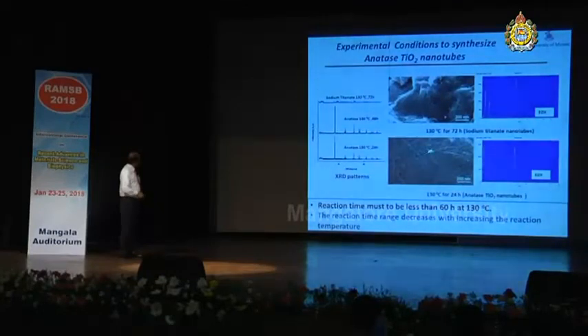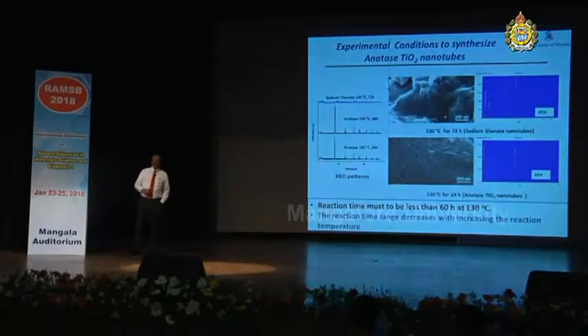This is the synthesis of titania nanotubes. There are so many papers on the synthesis of titania nanotubes, but what we have done is something different compared to what earlier people did. And in fact, we have obtained very nice, very long tubes at a temperature of 130 degrees C, and we varied the experimental duration, and when we increased the experimental duration, we started getting sodium titanate instead of titania. So we could get these nanotubes without any catalysts and others.